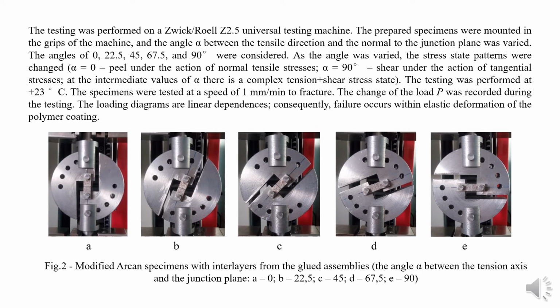Alpha equals 0: peel under the action of normal tensile stresses. Alpha equals 90 degrees: shear under the action of tangential stresses. At the intermediate values of alpha there is a complex tension plus shear stress state. The change of the load P was recorded during the testing. The loading diagrams are linear dependences. Consequently, failure occurs within elastic deformation of the polymer coating.